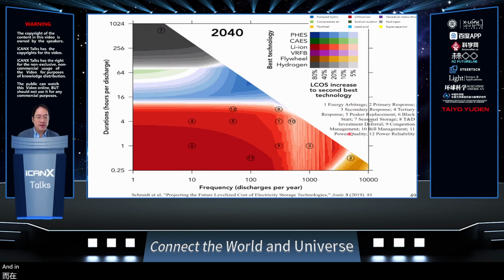And in 10 out of the 12 usage scenarios for the electrical grid, going from energy arbitrage to primary, secondary, tertiary response, to bill management, power quality, power reliability, the lithium-ion battery wins. So only when you have a very rapid response, the primary response, you can use the mechanical flywheel or the supercapacitor. And then for seasonal energy storage, you need to use a chemical fuel like hydrogen. So what this shows is that you really can have a big impact with these lithium-ion batteries.